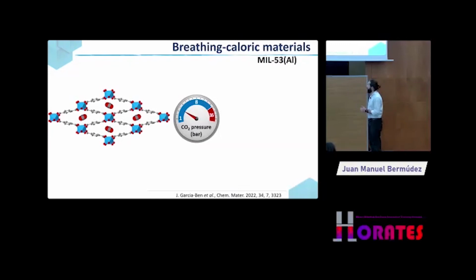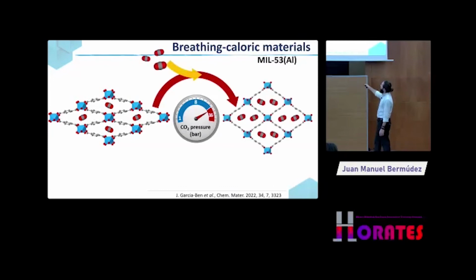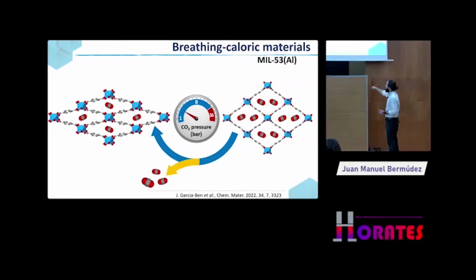That was the main field for the metal organic frameworks. Actually, they were promising materials because they were comparable by the time, and now they are much better than the zeolites for gas absorption, right? So this specific family of materials has a phase transition, which is called breathing transition, and consists of pressurizing the material with CO2, and this CO2 opens the cavities of your material, so you increase the capacity of absorption of the material, and then when you decrease the pressure, the transition is reversible.